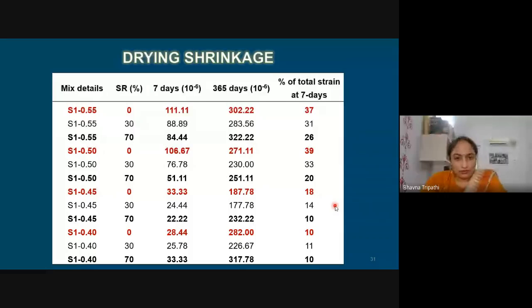Similarly, other mixes. Now, in a tabular form, we can analyze that shrinkage is bound to happen, but we are more interested in the total strain. How much is the total strain and how much is the strain in initial days? It is very important to monitor shrinkage strain in initial days, because at that time, if concrete develops micro cracks, those cracks will be widened, or they will lead to more cracking inside concrete.